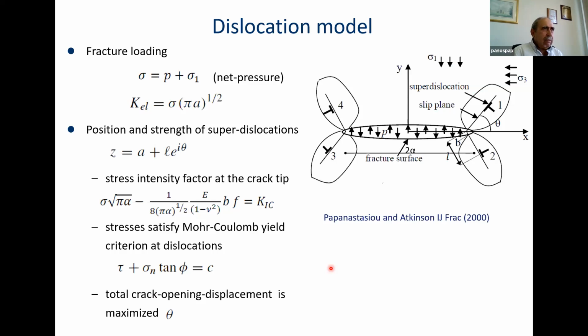And it's nice to have analytical models because in the analytical models, you can identify critical parameters. And we tried to develop an analytical model to take into account plasticity. And at that time with Professor Atkinson, who retired from Imperial College now, he was always a consultant for Schlumberger, we developed this model based on the dislocation theory. And with this model, we replace the distributed plasticity, you can see here, with super dislocations that are sitting in the center of gravity.